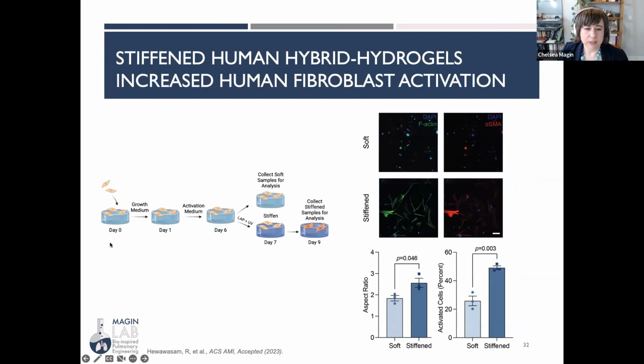Again, we grew these cells on our soft hydrogels and growth media for a couple days. Then we switched over to our activation media, which is just a lower concentration of serum. And then on day 6, half our samples were collected as soft samples, and the other half were stiffened, and then those were collected for analysis on day 9.